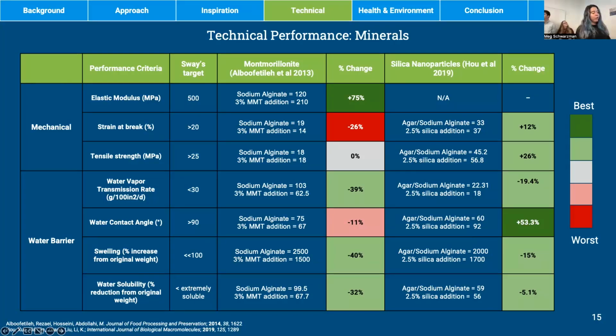In the mineral category, as mentioned, we identified two potential candidates for additions: montmorillonite, which is an aluminosilicate clay mineral, and silica nanoparticles. Both enhancements are going to be incorporated similarly into the matrix, where the minerals are first dissolved in water and then mixed into an aqueous solution of agar, whatever else, and plasticizers. And 1 to 3% by weight is a common choice for such addition.